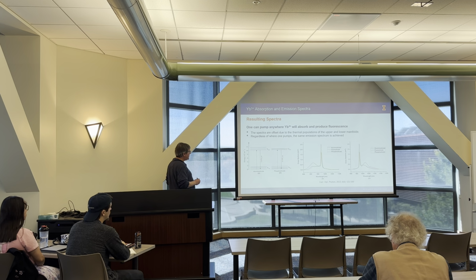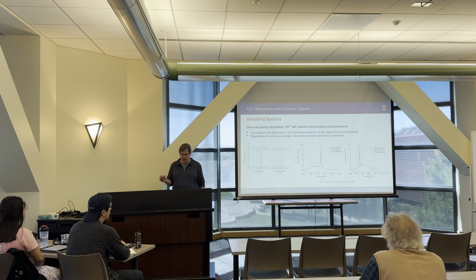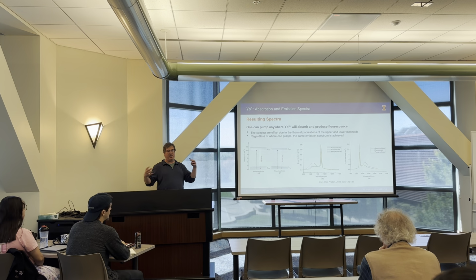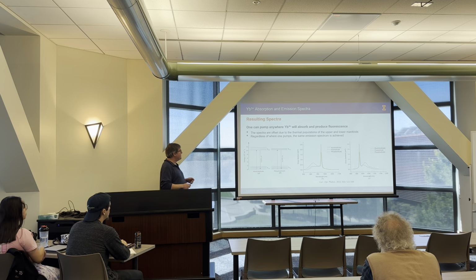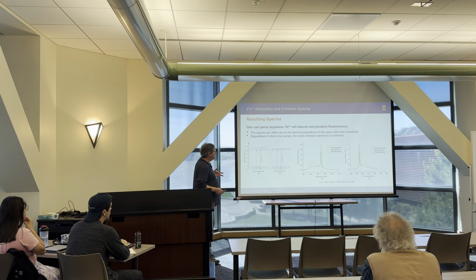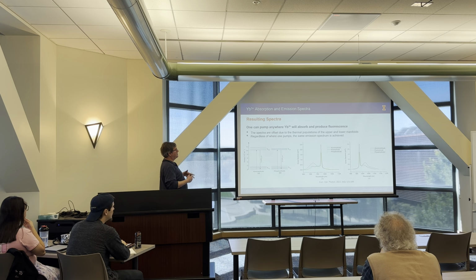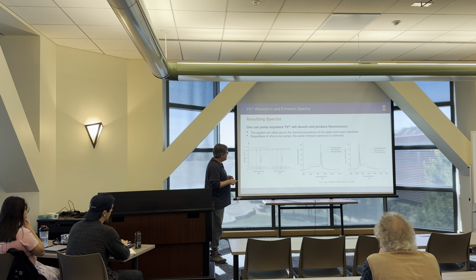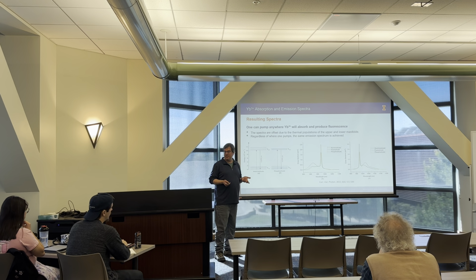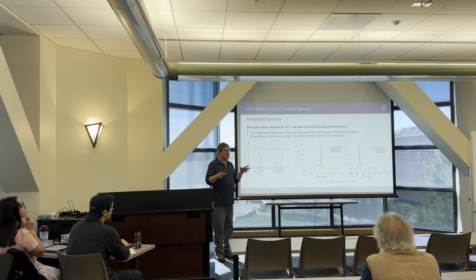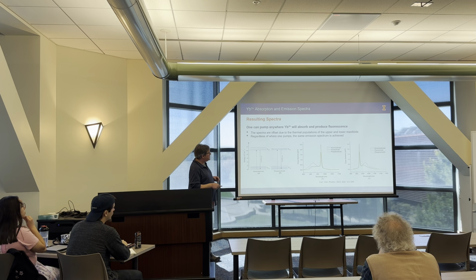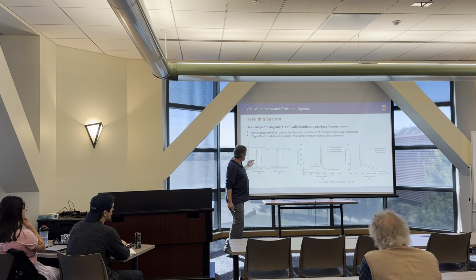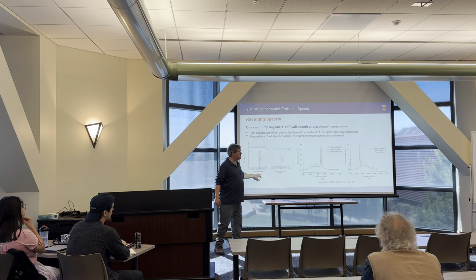The other thing, of course, we want to think about are the resulting spectra. Because we have these solids that are impacting the emission spectrum of the active ion, we have to consider that in our analysis of whether or not something may cool, or why it does or doesn't cool. Anyway, what I have shown here, again the same diagram from the previous slide, are plots of the absorption and emission cross sections. This is not the same as the luminescent spectrum, but it's close enough. You'll see that this changes quite a bit depending on what the host material is. But the idea is you want to pump with a low energy and emit with a higher energy.